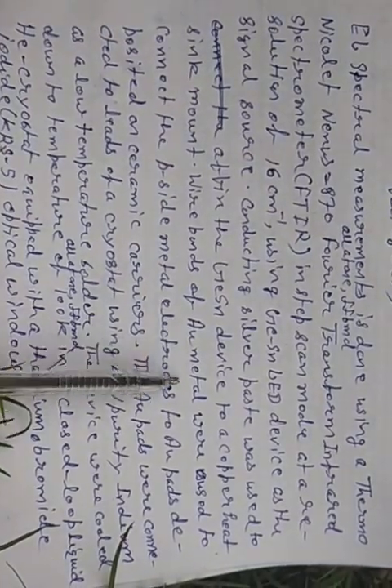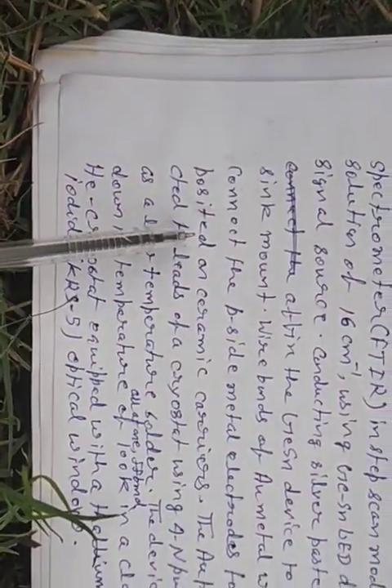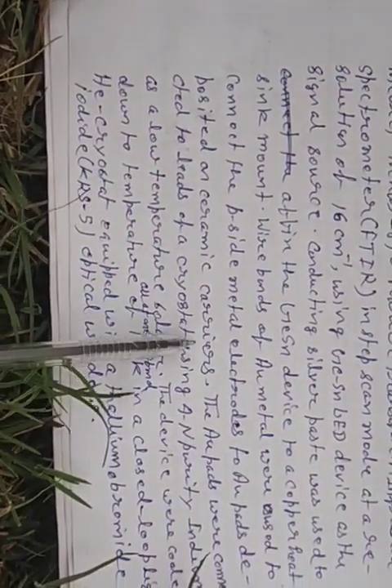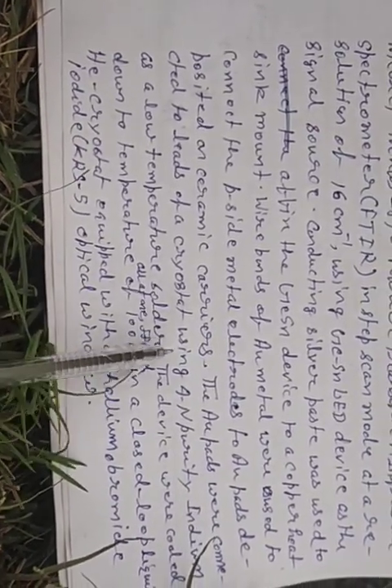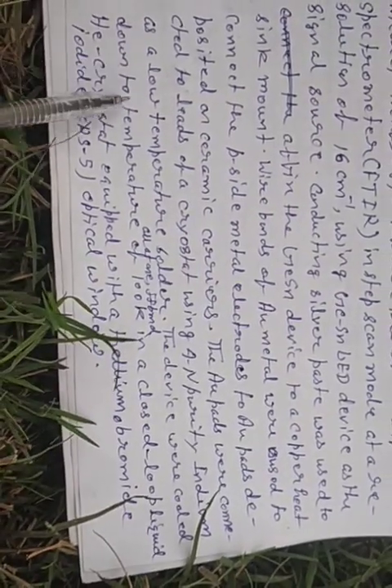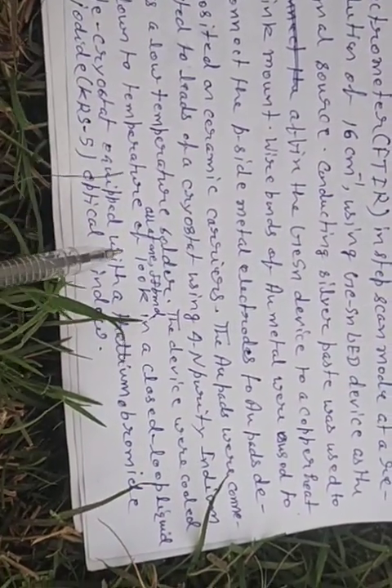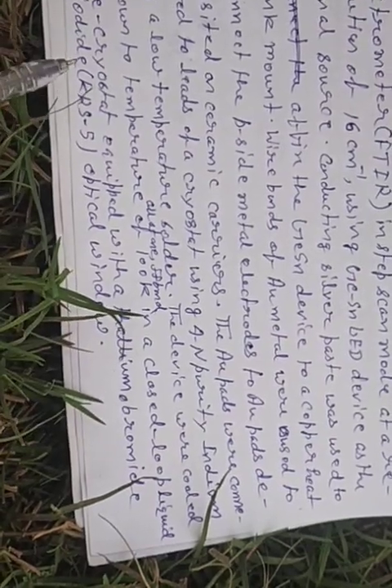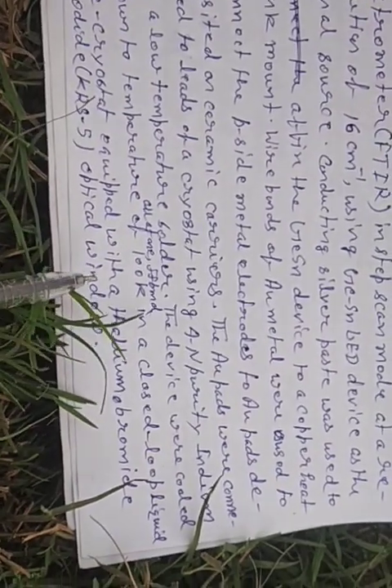Wire bonds of Au metal were used to connect the p-side metal electrodes to Au pads deposited on ceramic carriers. The Au pads were connected to the leads of a cryostat using 4N purity indium as low temperature solder. The device was cooled down to a temperature of 100 Kelvin in a closed loop liquid helium cryostat equipped with thallium bromo-iodide KRS-5 optical windows.